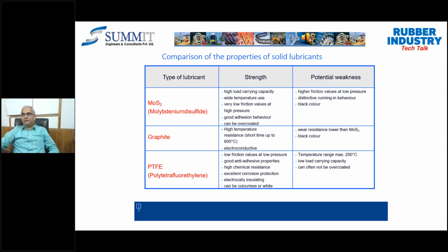But if I want to add any kind of pigment and make it color prone, or add a color additive, then probably I may not be able to use molybdenum disulfide. And then the only leftover option is PTFE. PTFE has many more advantages compared to molybdenum disulfide and graphite, and that's one of the reasons people are more and more using PTFE as the dry film lubrication.